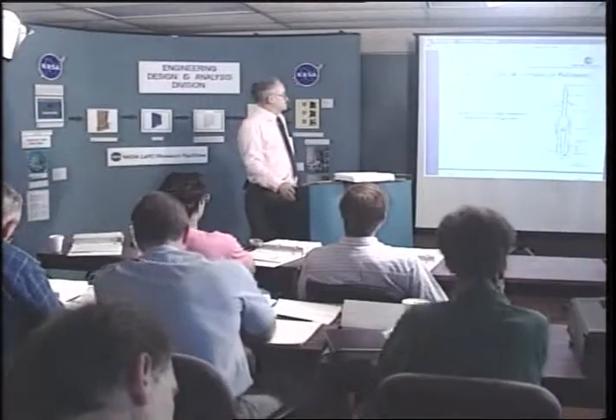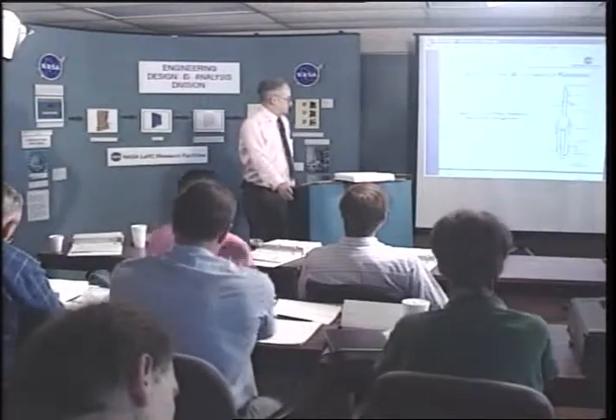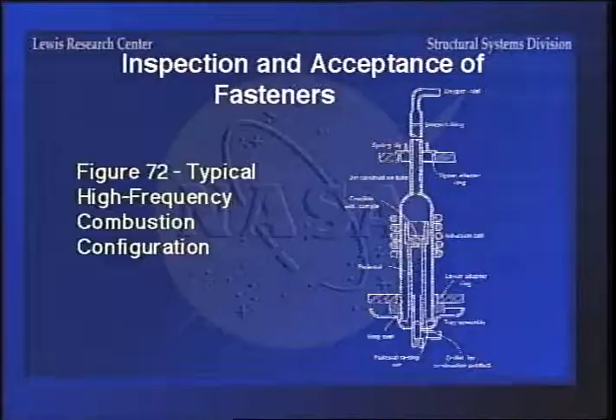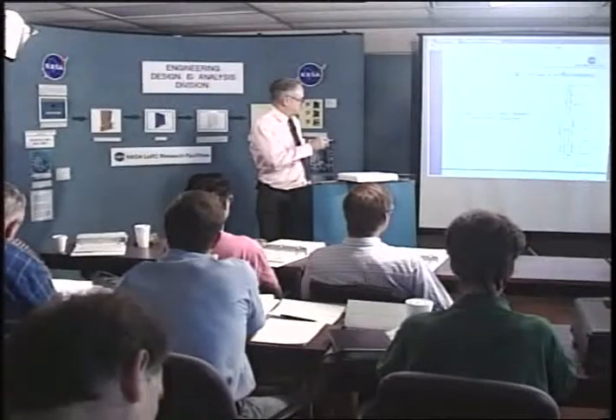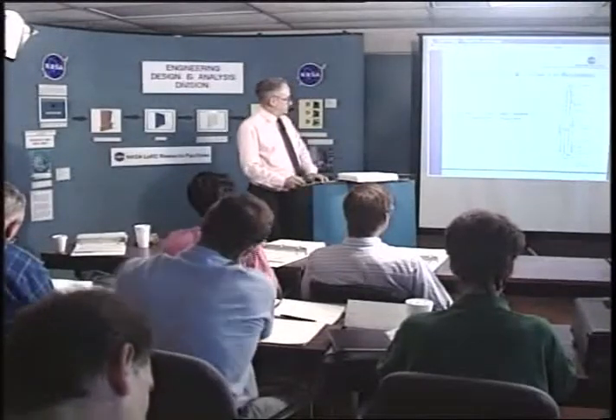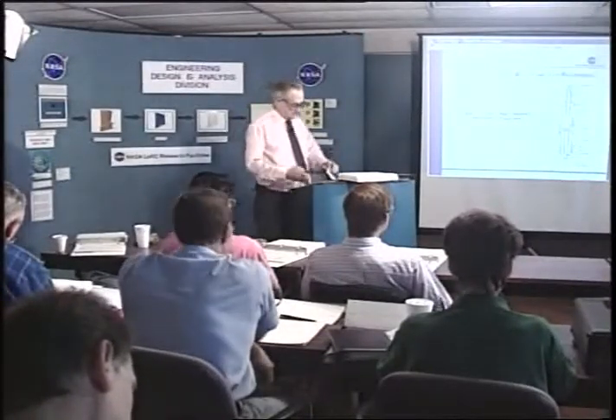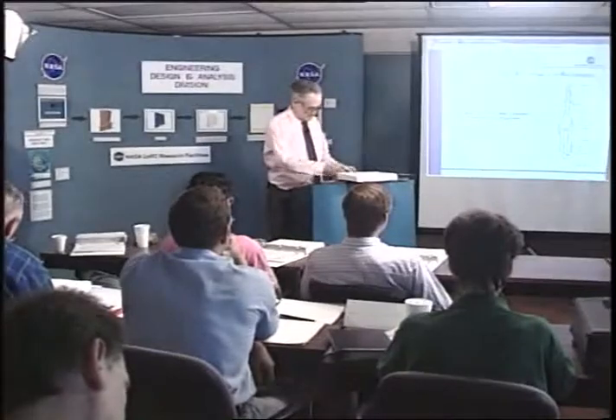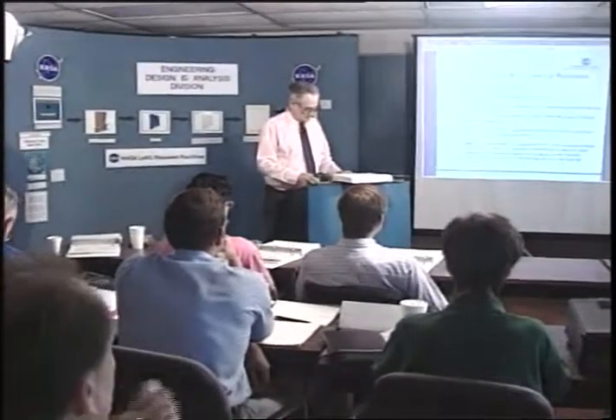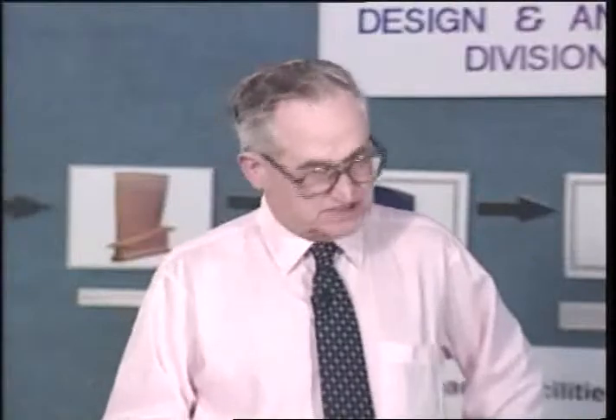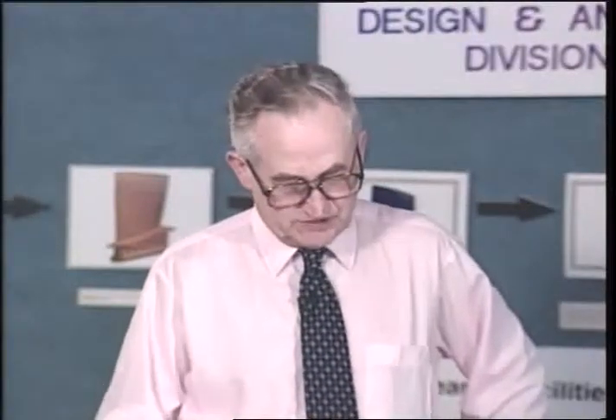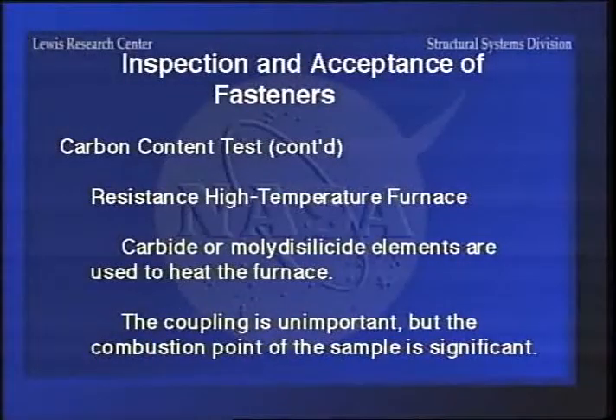We'll take a look at this furnace for checking the carbon content. This is just an ordinary induction coil - put the stuff in there, heat it up to about 2,600 degrees with oxygen and it will burn. Then you can proceed. Now on the resistance high temperature furnace, which is another one that's used, you have